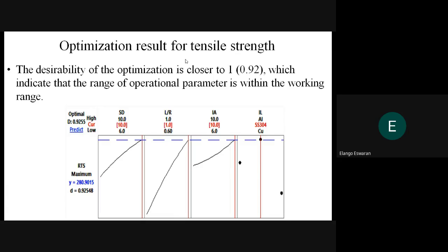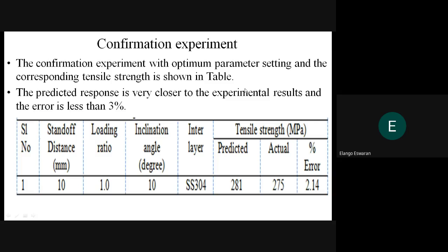The desirability of the optimum is closer to 1, that is 0.9255, which indicates that the range of operation parameters is within the working range. The confirmation experiment with the optimum parameter settings and the corresponding tensile strength is shown in the table. The predicted response is very close to the experimental results, and the error is less than 3%. That is, the error is only 2.14%.